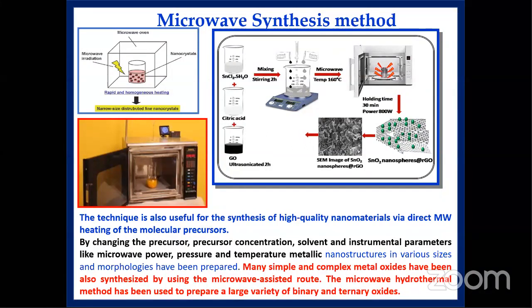You can see that by changing the precursor concentration, the solvent, and also instrumental parameters like microwave power, pressure, and temperature, you can get different sizes and morphologies. So many nanocomposite materials are prepared by this method, and binary and ternary components are also prepared by the microwave method. So it's a very simple and easy technique.